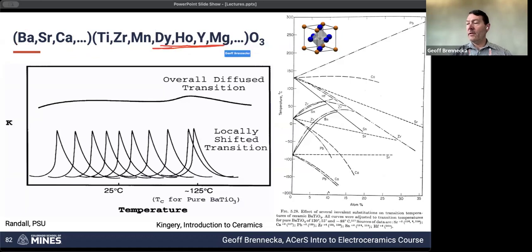Dysprosium, holmium, yttrium, magnesium, because magnesium is small enough that it actually goes on the B site largely instead of the A site, even though it's an alkaline earth. So these, and manganese, are all there to adjust the defect chemistry. So you're putting a 3+ onto a 4+ site, which is an acceptor dopant. That's to help mitigate oxygen vacancies if you need to sinter in a low PO2 atmosphere, for example.